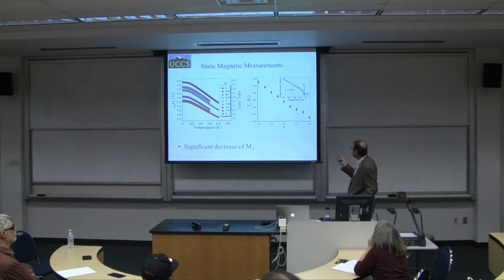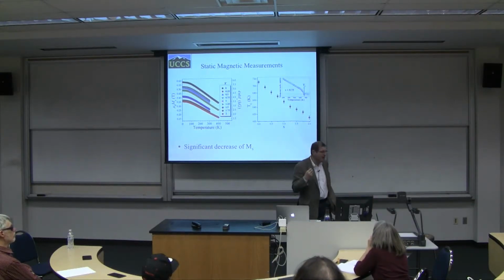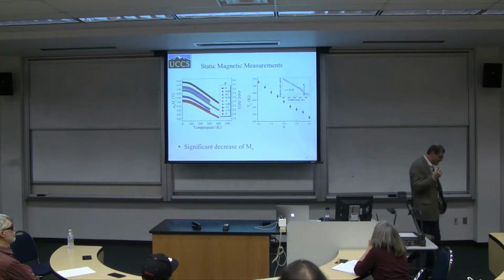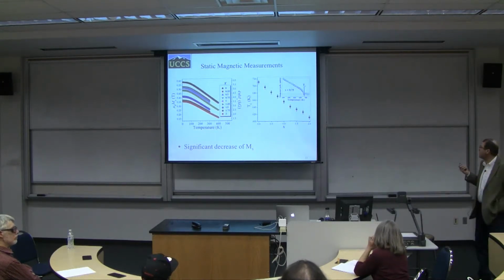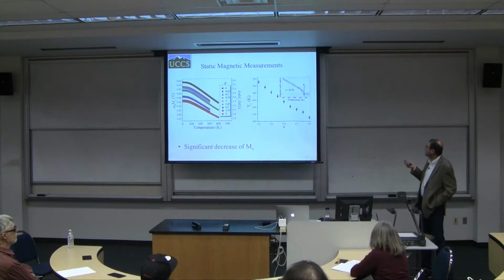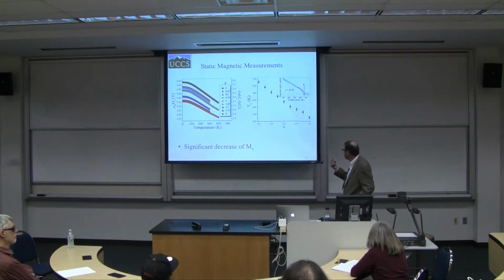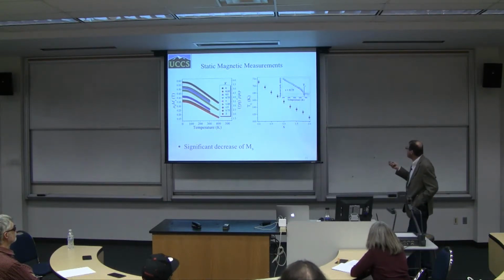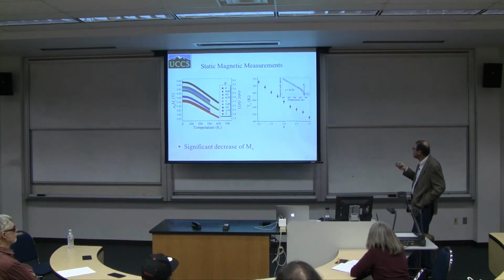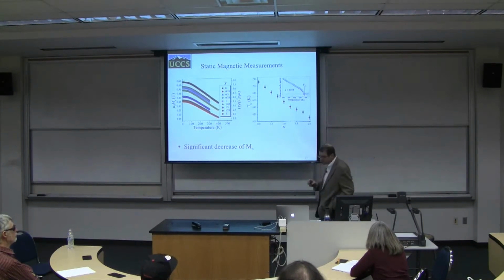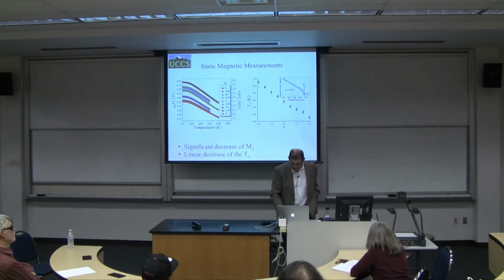And this is actually quite interesting that such deviation happened, because people have speculated and suggested that if we have a small concentration of aluminium, the aluminium will preferentially go to one of the sites which I have shown you on the previous graph, but above a certain concentration it goes randomly to some random sites, and therefore we have a deviation of Tc in this respect. Okay, so this is basically the conclusion, the linear decrease of temperature.